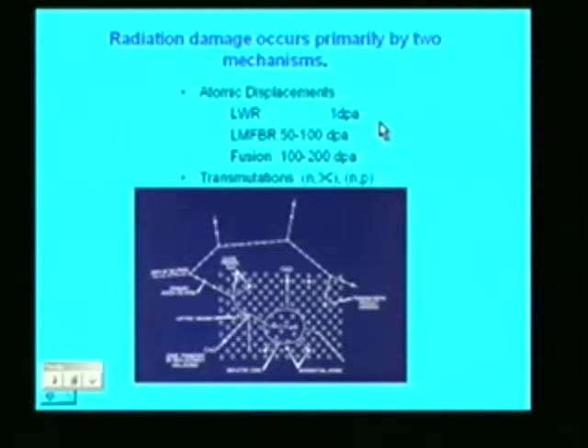We'll come back and discuss that a little bit more, but radiation damage occurs by primarily two mechanisms: atomic displacements and transmutations. Atomic displacements are shown diagrammatically here, where we have a neutron impinging upon materials, has to interact with an atom in the crystal and ejects a highly energetic and charged atom, which then can eject further atoms. So we get a cascade effect until there's no longer sufficient energy to eject an atom from its lattice. And the neutron can go on and also cause other interactions.